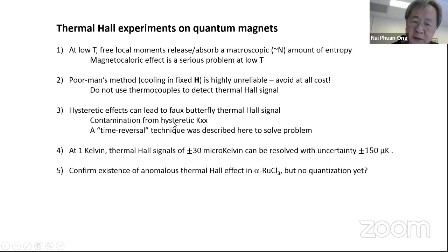Then there's a new concern when you look at magnetically ordered states. Hysteretic effects can lead to a fake butterfly thermal Hall signal unless you adopt the technique that Max unearthed. It can be called the time reversal or in-out-out technique. And this seems to effectively correct for all these hysteretic effects. When there's no thermal Hall signal, we explicitly see it as a 0 Hall signal. So this is something to watch out for.